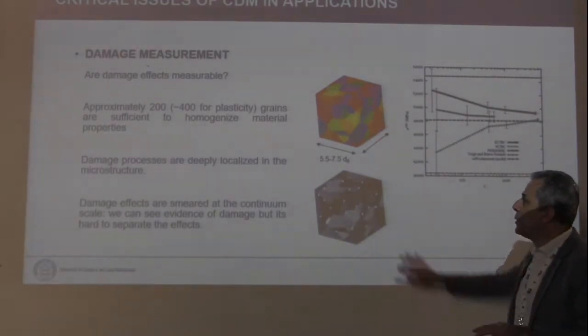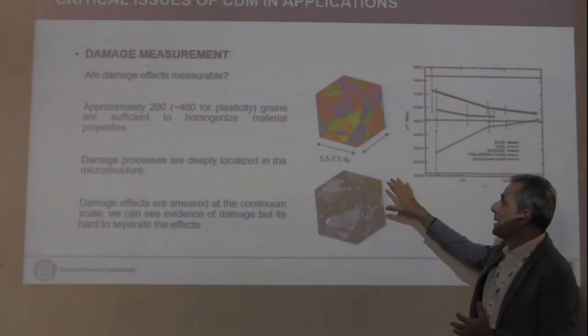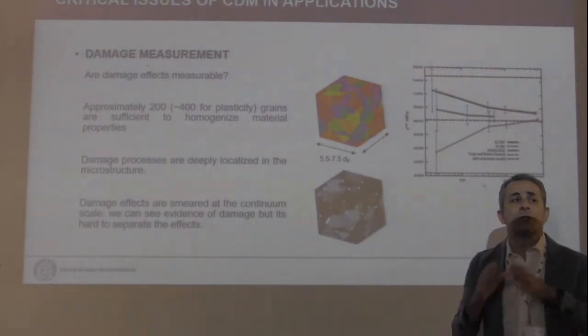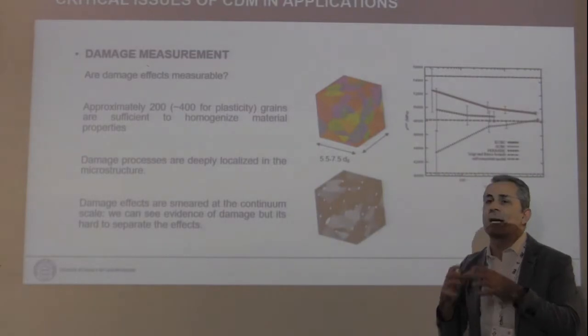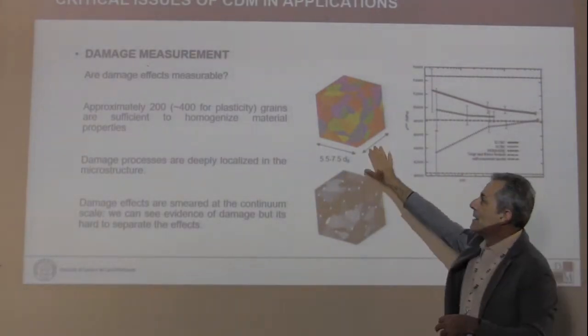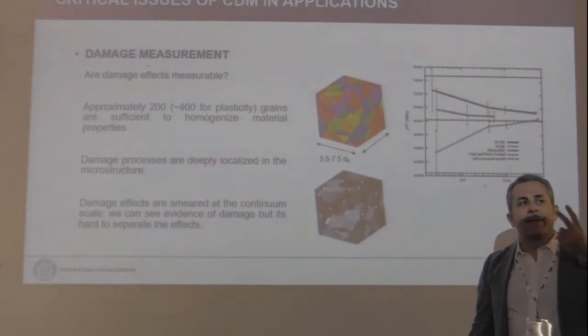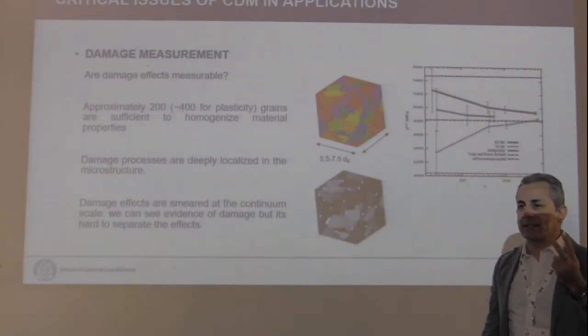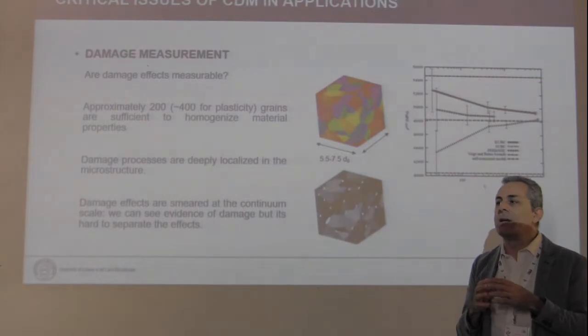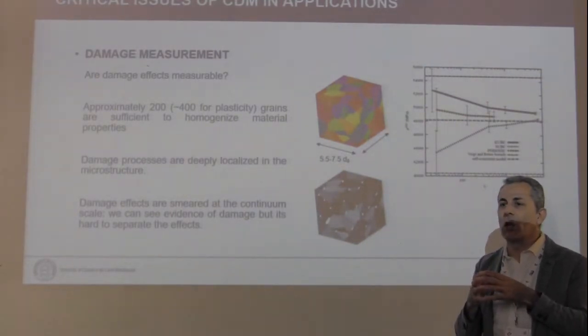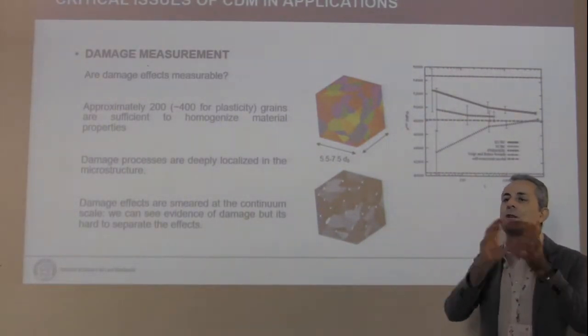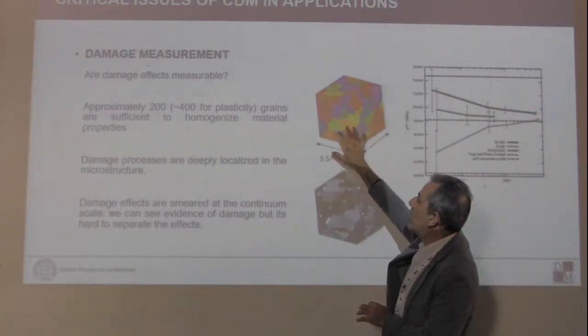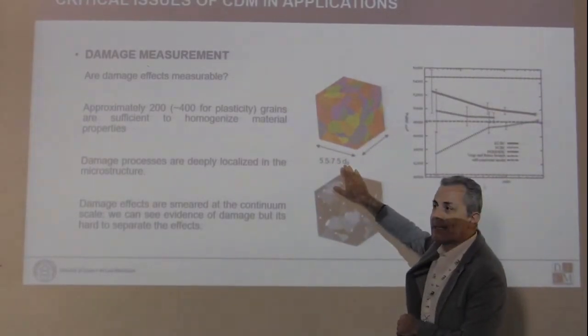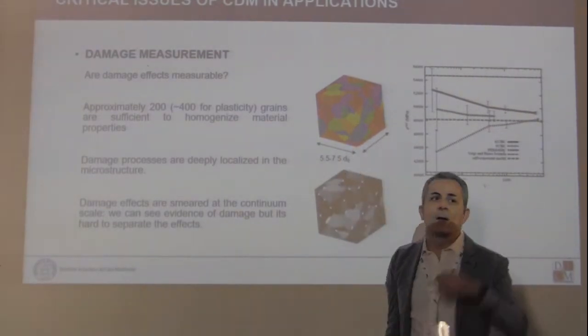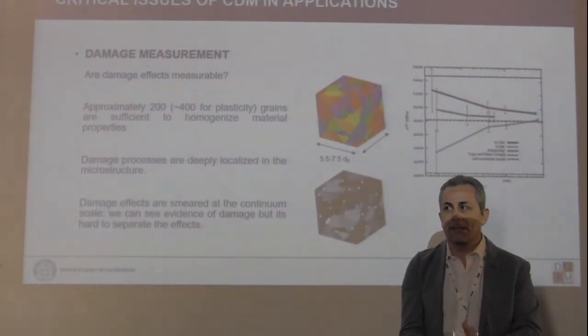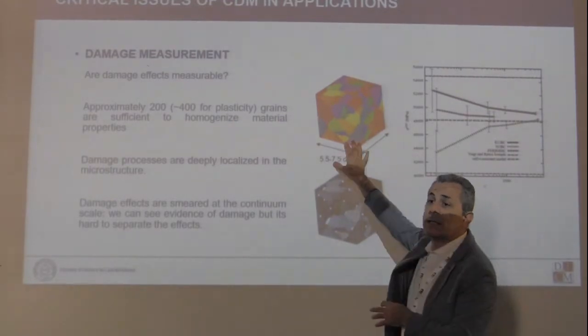That means that if we look from the computational point of view, a reference volume element, which is the minimum quantity that provides you the homogenized properties of the material, there is a proof that you need just 200 grains for metals, beyond which you can no longer discriminate the effect of the orientation of the grains. So it means that a volume 5 times the average grain size by 5 times returns you the homogenized properties. Damage is a much smaller scale than this volume.